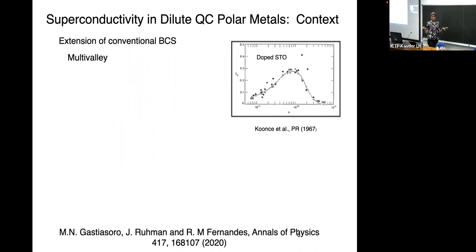So he wrote down a theory, and this is one of the few cases where it was predicted, then he went downstairs to the experimental lab of Koonce et al. And he calculated a TC as a function of density. He got a nice dome. And then he predicted it, and they did the measurement. And this is what they got. You see TC as a function of density. This is niobium doped. And with all due respect, Andy, you said, if theory and experiment match beautifully, then it must be right. Beware of theorists, and this will include me, showing you fits to domes.